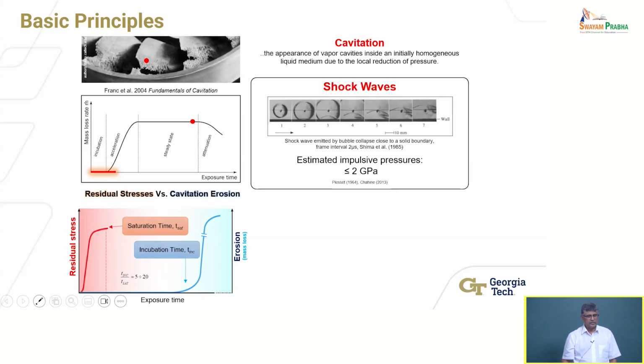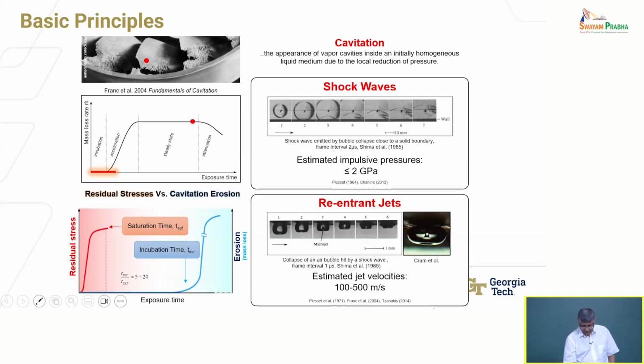I already said this, you can generate very high impulse pressures. Each of these bubble collapse events can generate localized pressures on the order of gigapascals, which is sufficient for you to deform the material. And you will also generate what are called reentrant jets. These are micro jets that are formed as the bubbles collapse. You can think of it as water coming in, and there is a very small gap. The gap is reduced as the bubble is collapsing because it's shrinking. It'll speed up the water and produce very, very high speed jets, micro jets, on the order of 500 meters per second, extremely high speeds.